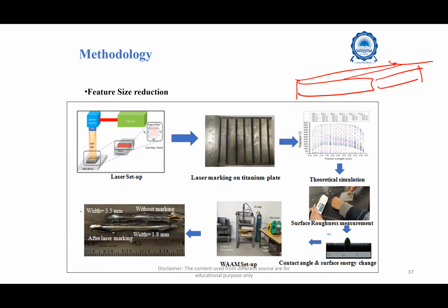To give you a better clarity, this is the arc without marking. This is the structure which we have fabricated with wire arc without laser marking, and this is the structure which we have fabricated with laser marking. Without laser marking, your width is around 3.5 mm, whereas with marking at the same parameters, your width is around 1.8 mm. This is because you are manipulating the arc with respect to the surface roughness which you are trying to induce on the surface.